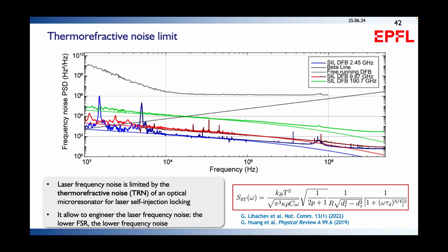Let's first look at the laser line width. One of the surprising aspects of these lasers is that due to the very high quality factor, these lasers operate basically at a thermodynamic limit of line width. And where does the thermodynamic limit come from? It comes from temperature fluctuations. So ultimately, these self-injection locked lasers are limited by frequency noise that is uniquely determined just by the temperature fluctuations of the material itself that are innate to the thermodynamics. It's called thermorefractive noise. And the thermorefractive noise we can engineer by simply making the cavity longer. We can reduce the noise process.